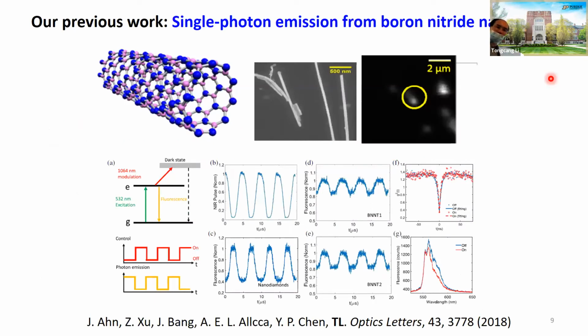Before this was discovered, we had been working on color centers in boron nitride. For example, here's our paper in 2018, about single photon emission from boron nitride nanotube. We found that we can have some defect on the nanotube, and it is quite a good single photon emitter. And we can use another laser to modulate the single photon emission. At the time we were also thinking about spin defects. Once we read their paper, we felt this is quite interesting, and we wanted to go ahead with the spin defect.